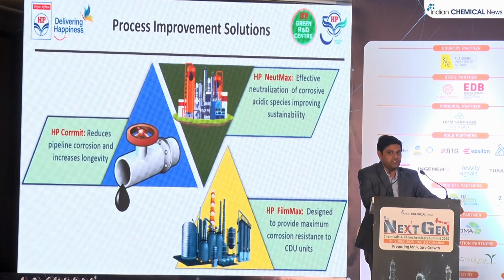Then from these crude chemicals, I'll move to process improvement solutions. These are some of our corrosion inhibitor offerings. These are already there in the market, but these products have been developed to see whether we can optimize the dosage. We have seen that after using this chemical, there is a 15 to 20% reduction in the dosage, and we got the same efficiency as the commercial additives available in the market.